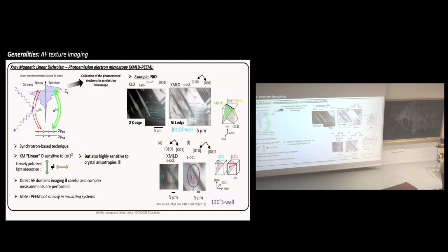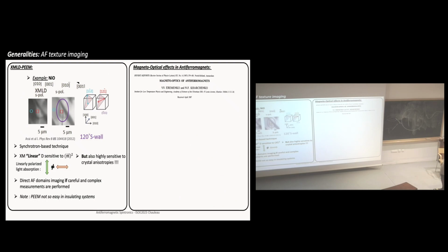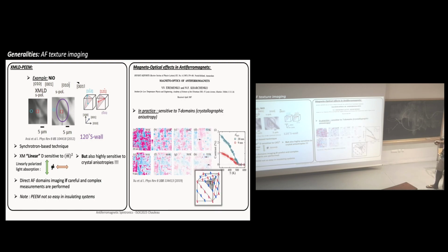And last but not least, there are also a lot of magneto-optical effects in antiferromagnets. Here I put an old reference. They are full of detail on this, but it's quite complicated. There are a lot of them, so I will not go through them, but I will just advertise one of the recent studies. In practice, what interests us is that we see very well the T domains, which are related to this crystallographic anisotropy. This is, for example, an example where you have the pink and blue T domain orientation. You have two possibilities if you look at them, if you are perpendicular or in line with the T domains.